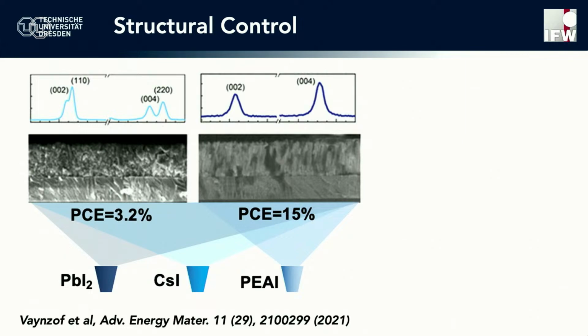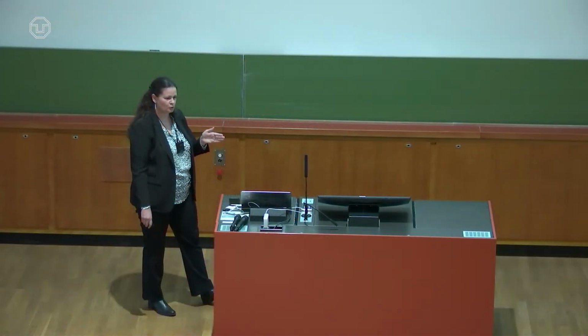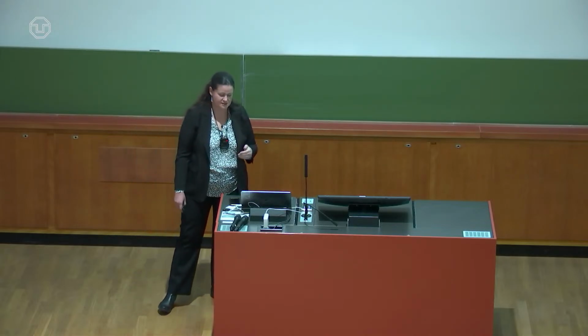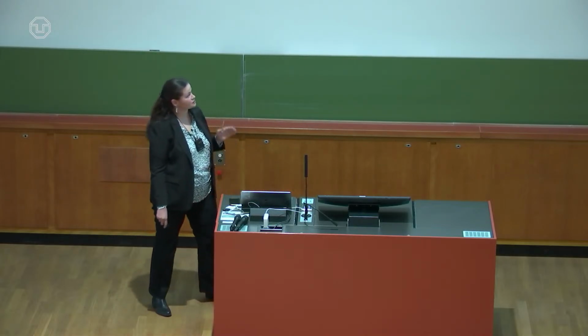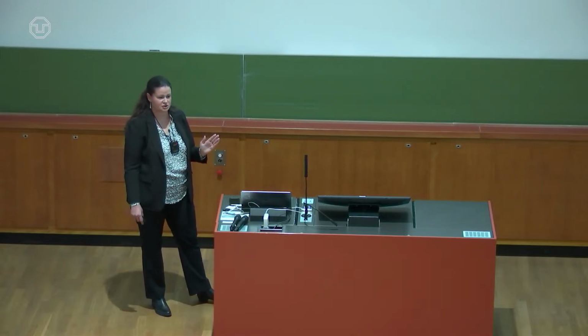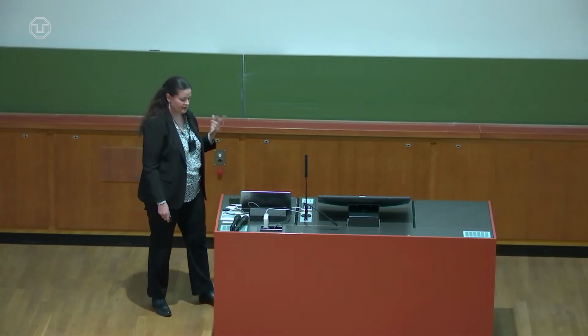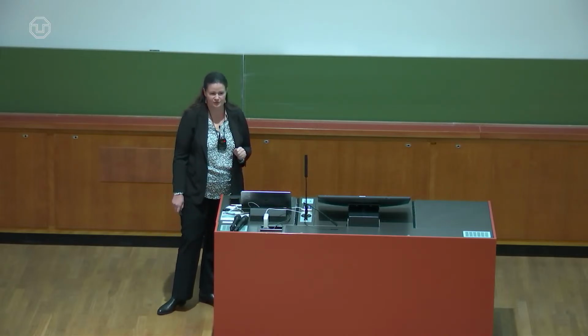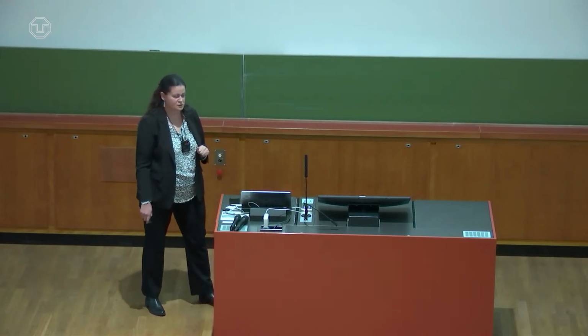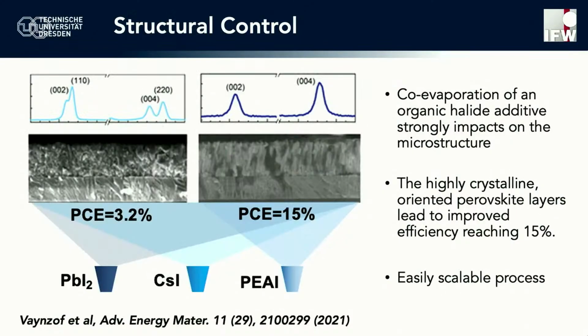Then we added a small amount of additive that we co-evaporate along the perovskite precursors, called PEAI. In this case, you can clearly see the effect on microstructure. You have a columnar growth where the grains grow in a very ordered fashion. And you can also see it in the X-ray diffractogram, because you see that there is a single crystalline orientation. So all the grains grow in the same way. And the performance significantly increased to 15%. For an inorganic perovskite, this is already very promising. And of course, again, the advantage is that you can very easily scale up the thermal evaporated films to mini